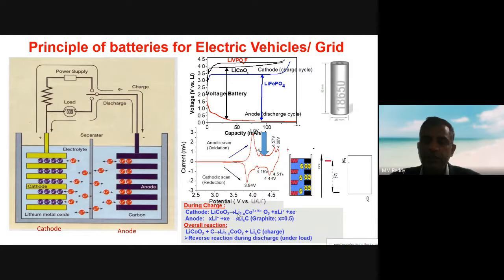For the same material, lithium cobalt oxide, the galvanic voltage versus capacity gives something like 3.9 or 4 volts. Remember, this voltage depends on which type of cathode is used; these are all layer type. Lithium cobalt oxide is a well-known layer type compound. When we want a good voltage, we need a difference between charge and discharge. Now, people may ask, why don't you use other layered compounds, for example tungsten oxide or molybdenum sulfide? Yes, we can use them.